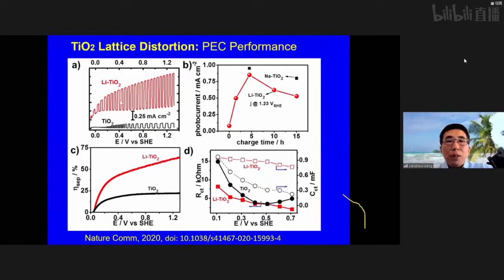This basically provides a good driving force for the photocurrent to be increased compared with the non-inserted ones, and in this case it also reaches a relatively high photocurrent density. This gives us another example: when you structurally or compositionally tune the materials, you are able to reach relatively high performance in the same type of materials.